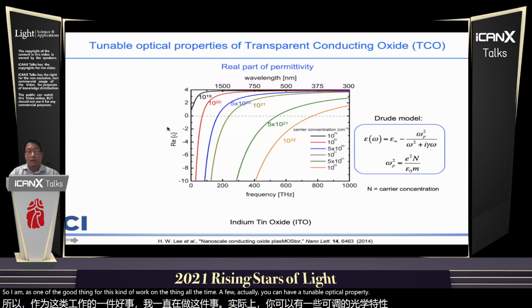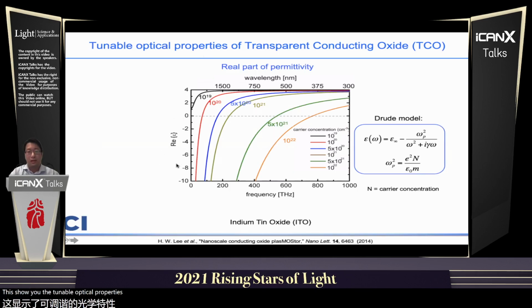To show you the tunable optical property, I'm showing here the real part of permittivity against the frequency or the wavelength of light, using a standard free-electron Drude model with a carrier concentration N and plasma frequency here, assuming indium tin oxide material. And you can see that by changing the carrier concentration of the material, you can shift the dispersion to a different wavelength.